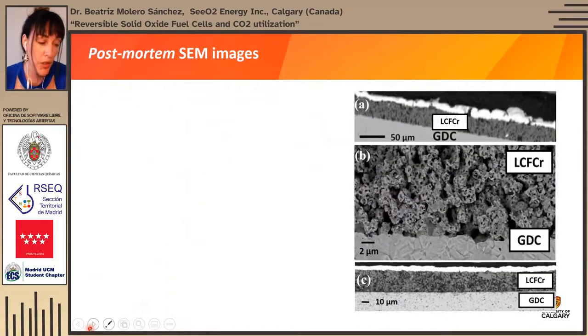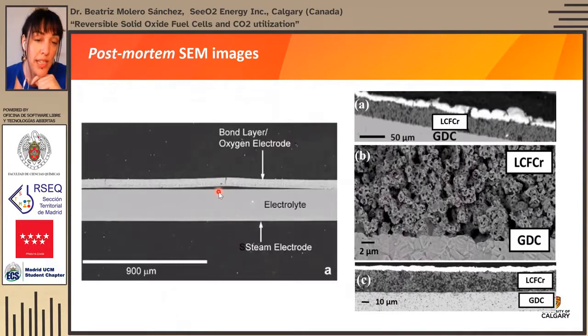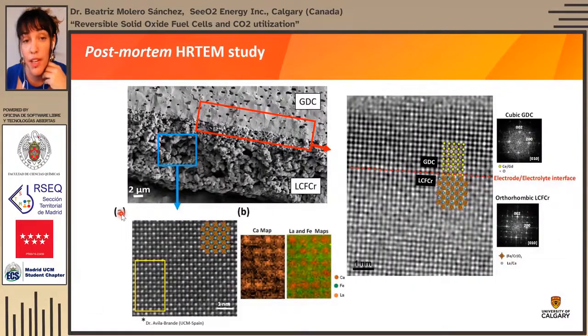Just to give you a quick visual representation of how these devices look after post-mortem, after being tested, you can see these porous electrodes and this thick electrolyte here. And when I mentioned the problem of physical delamination, you can see it really well in this SEM here, they actually physically delaminate and then they would stop working. So we did a lot of work to avoid that, and the compositions that we chose do not delaminate. And here is some proof of that, which was performed in collaboration with Dr. Avila at the Universidad Complutense of Madrid. You can clearly see, after hundreds of hours of testing, that the delamination problem is not there.